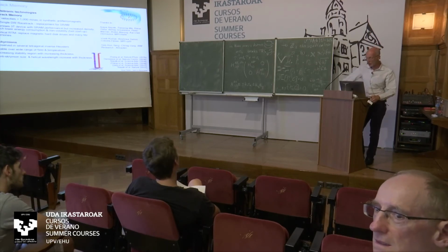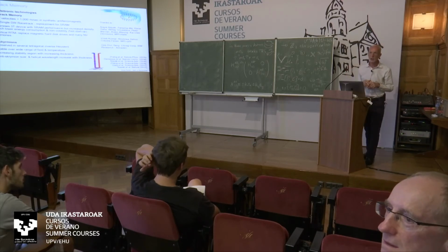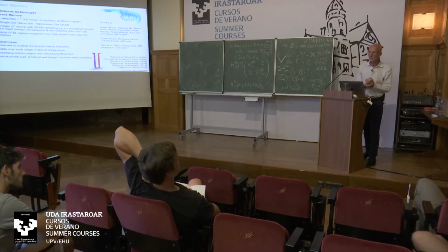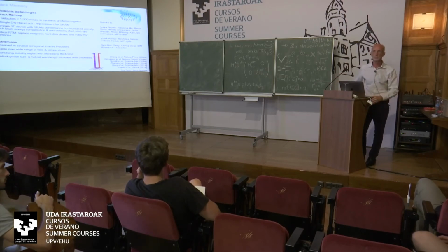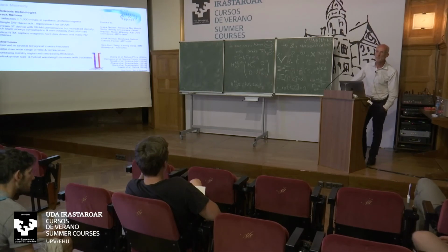Skyrmions, that's a very interesting question. We think it's not possible because the local crystal symmetry determines whether you have a skyrmion or an antiskyrmion. An antiskyrmion arises because you have different components of this Dzyaloshinskii-Moriya exchange in different crystallographic directions, stabilizing Néel or Bloch walls. So we don't think it's possible to have skyrmions and antiskyrmions in the same material.